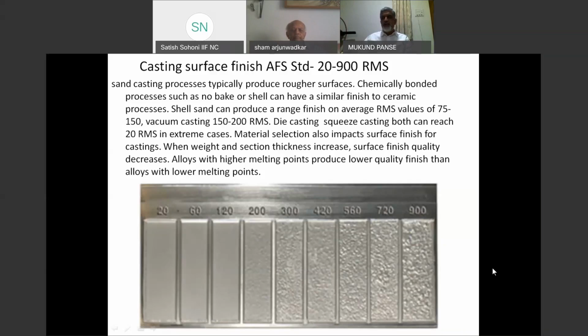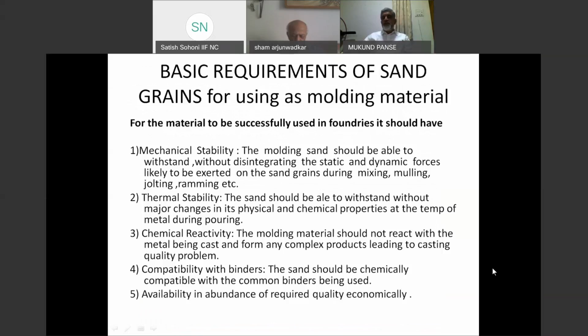You should try and see that you don't touch 900 or cross it. The surface finish you get is mainly dependent on the fineness of the sand. The finer the sand, the better texture you will get. However, when you are pouring heavier castings, the fine sand will get fused and a sand fused layer will be there. So you have to use coarser sand and the original texture, that is RMS value, will be on a higher side. So we'll see what are the basic requirements of sand grains for using as a molding material so that you get a better surface finish.